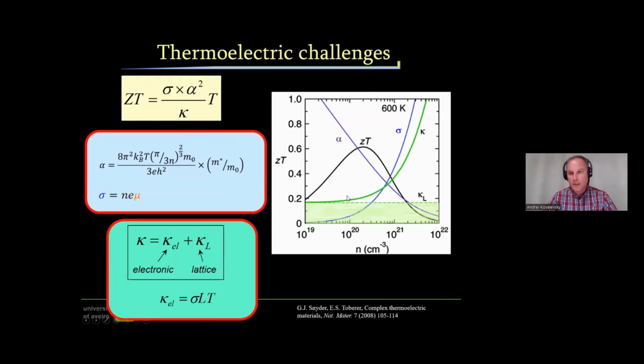Whenever we are, for example, doping our semiconductor and introducing charge carriers, we have an increase in electrical conductivity, everything is fine, but at the same time we have a decrease in Seebeck coefficient. After a certain concentration of charge carriers, we can have an increase in thermal conductivity, and all this together doesn't work very well, as you can see.